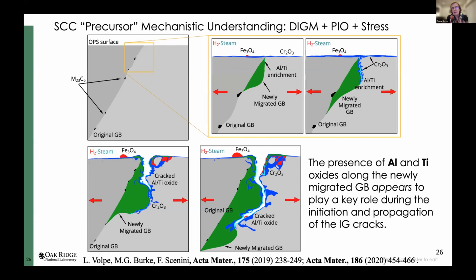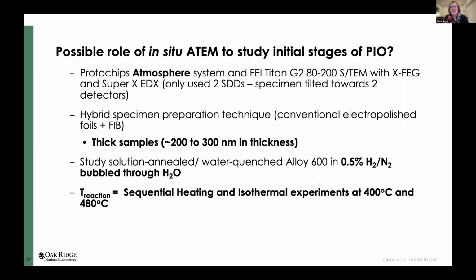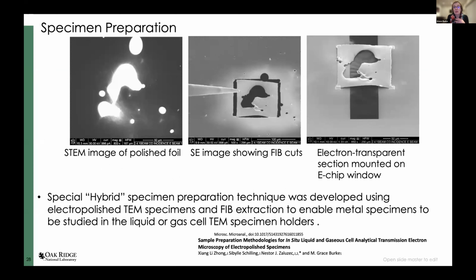What I want to do is just show you what we can do with in situ work to study this. And this is again using the Protochips atmosphere system in our Titan. The one thing that I want to highlight for you is that the specimens that we are exposing are thick specimens. I know it doesn't sound like it's very logical, but we need to make sure that we're not governed by surface effects. So we need to be thick. And we're going to do very simply bubbling gas, hydrogen gas through water. We looked at several temperatures, and I'll just show you some examples.